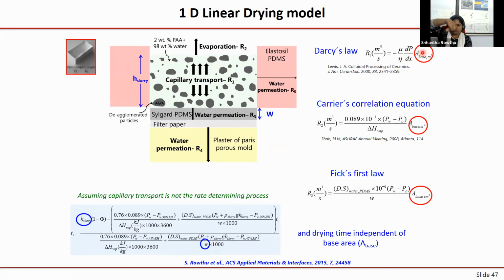So that means, am I pouring my slurry on 1 millimeter square area or 10 millimeter square area? What is that area on which I'm pouring? Because, for example, in the kitchen, if you want to cool down your hot milk before you feed it to your baby, we normally take a very big area and try to cool it down easily, right? So that was your base cross-sectional area. All these three terms actually contain the base cross-sectional area, but your drying time is independent of this base cross-sectional area. So if I pour it on 1 millimeter square or 100 millimeter square or 1 kilometer square area, the drying time will be the same.